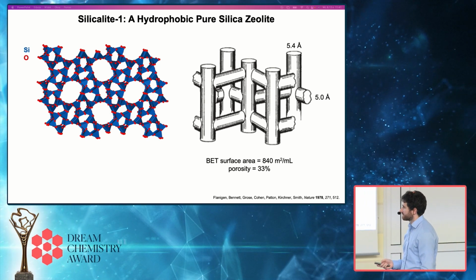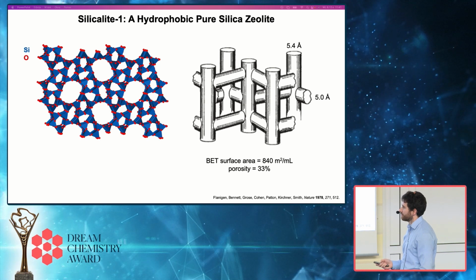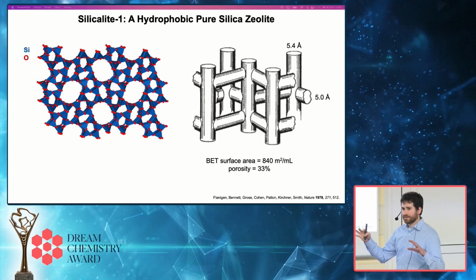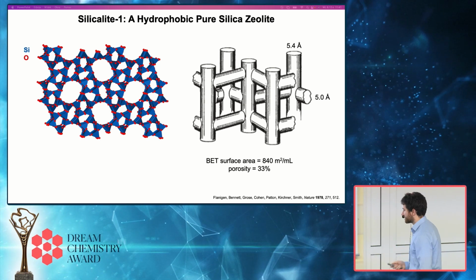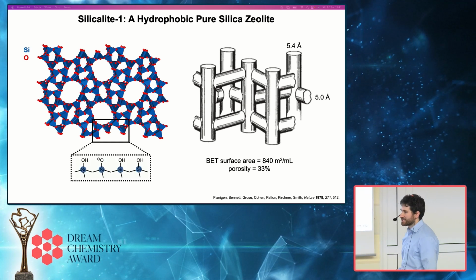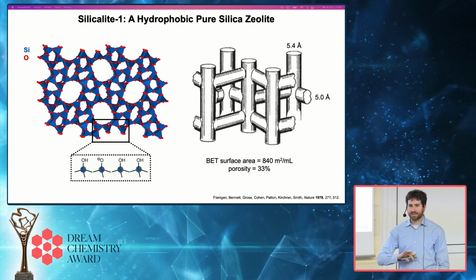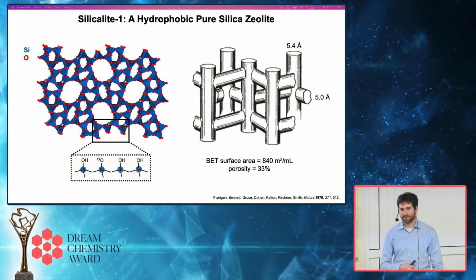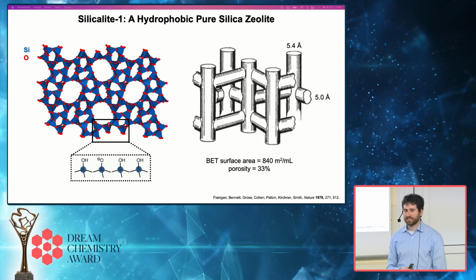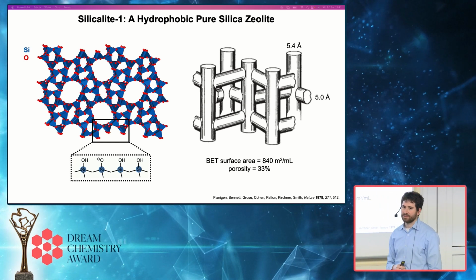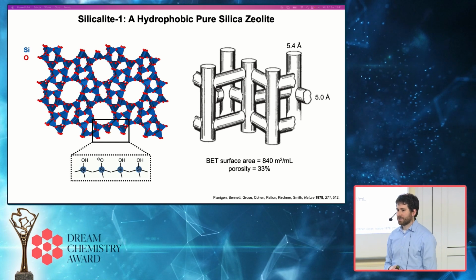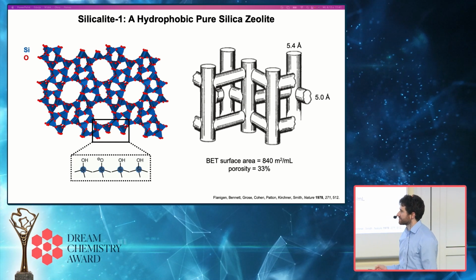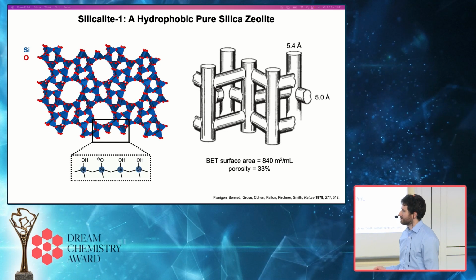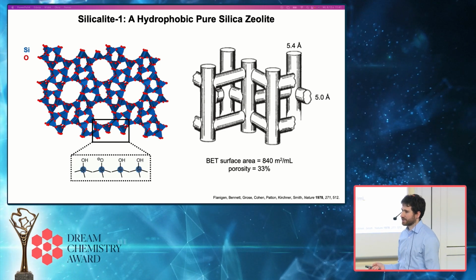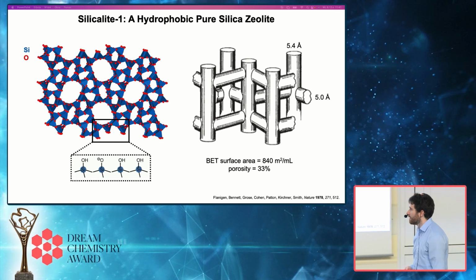The internal surface of this material contains a porous network of about 0.5 nanometer pores that are interconnected in 3 dimensions. The other reason we were really excited about this material was that its external surface, the external surface of pure silica zeolites, are terminated in silanol groups, and these silanol groups can be deprotonated in water. And so what you wind up with is an external surface that's intrinsically hydrophilic. So you have a hydrophilic external surface and a very hydrophobic internal surface.